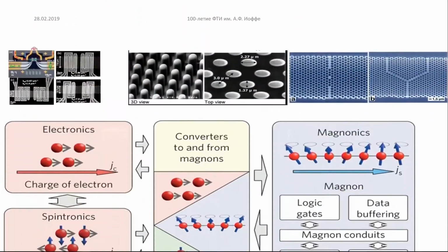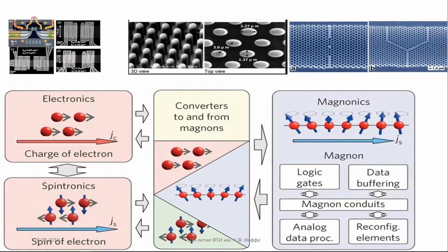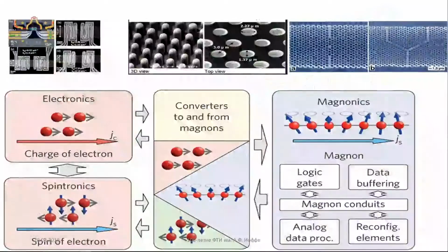So typical structures for these magnonic devices: you can process the films with some periodic or aperiodic structures. You can create so-called nanodots, as shown here, for example. And the size can be from microns up to submicrons or even nanostructures. You can make periodic structures, and you can make defects. As in photonics, you can excite spin waves in various ways, and they can propagate considering the structure which you produce in these films. So it's already a repetition of the previous structure, and in fact, you can produce all of these magnonic networks, similar to electronic networks and similar to electronics excitation devices.